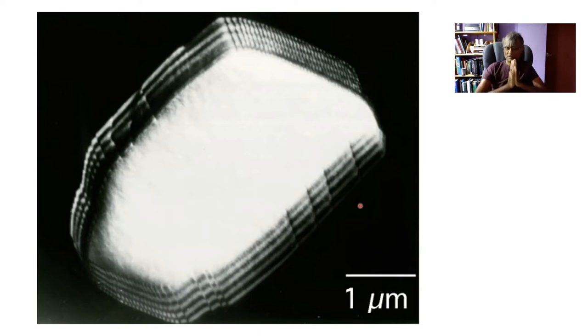Okay, so these are real structures that we actually observe in the interface, because these dislocations have strain fields, and those strain fields can be imaged in a transmission electron microscope because they give rise to local variations in the lattice parameters, so the diffraction condition is altered. So we can identify the dislocations, and we can even measure their Burgers vectors by doing something called a g dot b analysis, which I don't want you to worry about.